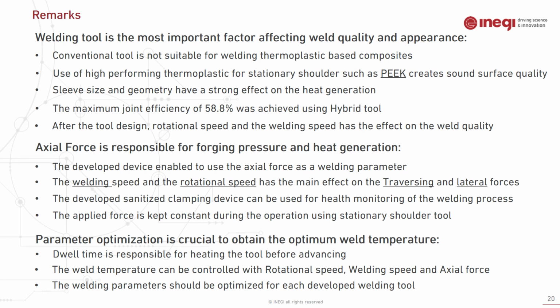Parameter optimization is a crucial factor to obtain optimum weld temperature and quality, and dwell time is responsible for heating the tool before advancing, but for using the hybrid tool, preheating the tool was required. The weld temperature can be controlled with rotational speed, welding speed, and axial force, and the welding parameters should be optimized for each individual welding tool.